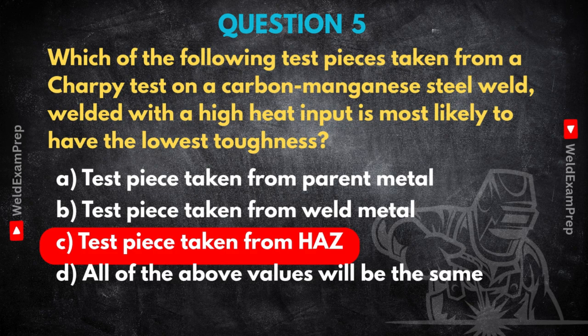Right, slow cooling. And that specific thermal cycle, especially in CMn steels, causes the grains in the metal structure to grow quite large. We call it the coarse grain heat affected zone, or CGHAZ. Big grains are bad for toughness. Generally, yes, especially in these steels. That grain coarsening, plus the slower cooling, can also lead to some undesirable microstructures, forming things like Widmanstätten ferrite or coarse pearlite. These structures are just inherently less tough, more brittle, especially when it gets cold or if it takes a sudden knock. I see.